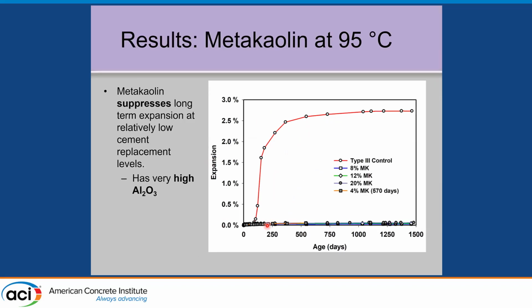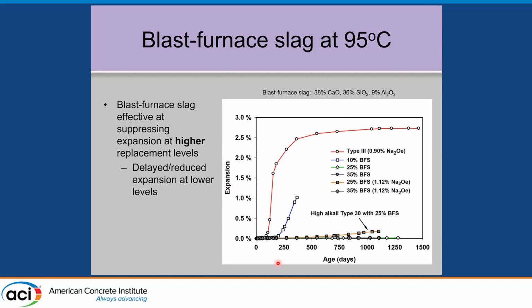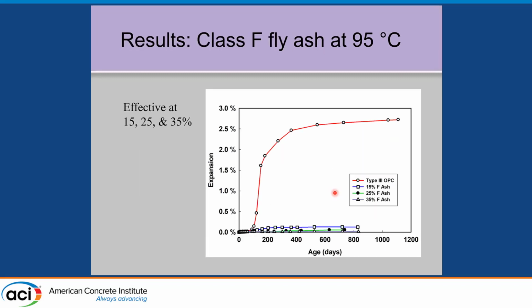However, metakaolin, which is aluminous, with that same cement, you can see even at 8%, 12%, even 4% controlled the DEF. And so the alumina seems to have a play in this. And you see the same thing with blast furnace slag, which has alumina, not as much as metakaolin. Even 10% slag helped, but not sufficiently. And a really high alkali cement, type 3, with 25% slag wasn't enough either. But you can see that generally 25 to 35% slag was sufficient to control the DEF. Class F fly ashes were effective at 15 through 35% in controlling expansion.